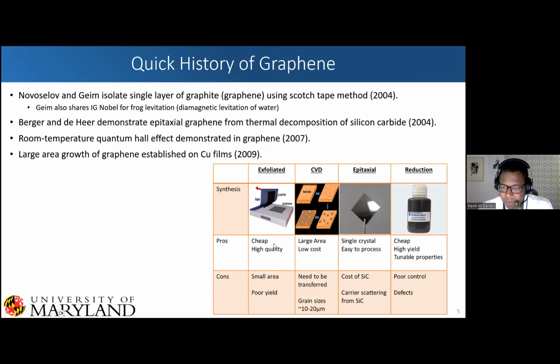And so exfoliated graphene and CVD graphene, of course, very cheap. You can get CVD graphene in very large area at low cost. But then you start getting into really poor yields, small areas, small grain sizes. And so the remainder of the talk is really going to be about epitaxial graphene. So we get single crystal graphene, very easy to process. It's completely CMOS compatible. But the biggest issue is the cost of silicon carbide, which luckily for us